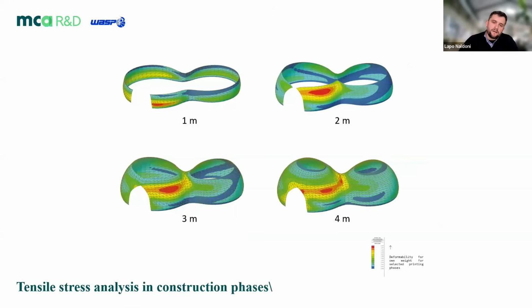Here you can see a simulation, an analysis that we made in order to understand, during the construction phase, the stability of the wall. Because as you can imagine, when the domes are closed, they are so stable, but at the beginning it was an open wall, so the stability was not perfect. So we performed this test to be sure about the stability of the system, and with those results, we understood where to add some support, some wood support, in order to help us to have a safer building site.